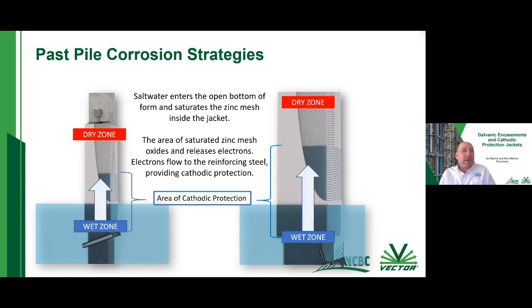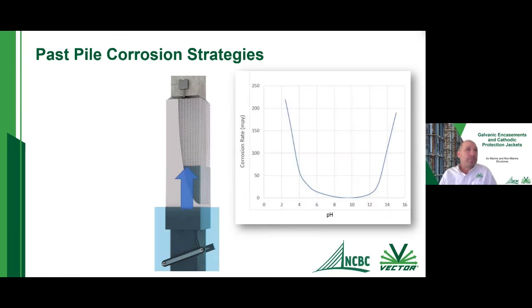So what ends up happening is the zinc starts to passivate, and there's a couple of slides coming up where I'll talk about this. As I mentioned, you're going to take that bulk anode that was placed underneath the jacket, and this is going to provide cathodic protection to everything in the water zone. So we have our electrolyte that we talked about before. We're going to use our salt water here as our electrolyte, and this bulk anode is going to protect the pile in our submerged zone.